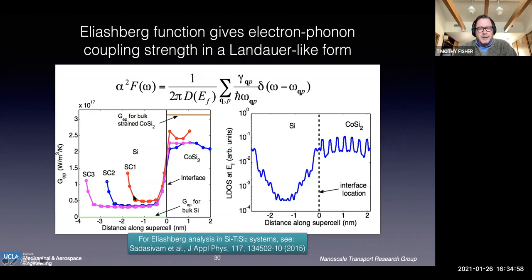The other thing that we did is we looked at different supercell sizes, 1, 2, and 3 here. And once we got to a place where, as we moved away from the interface at 0, the coupling strength was constant along here, then we said, oh, that's converged, all right? And so this is the coupling coefficient. This is the electron-phonon coupling coefficient. This is just to show you all the little steps you have to make in atomistic modeling to be able to come up with something like this.